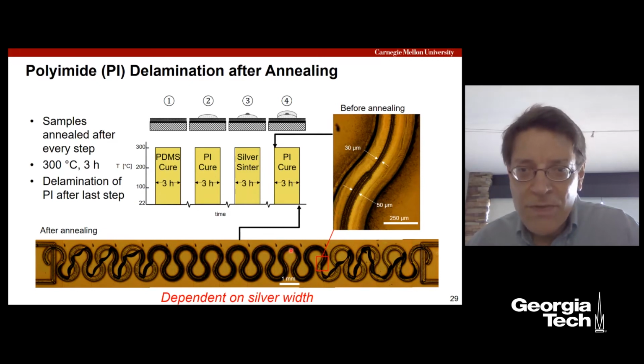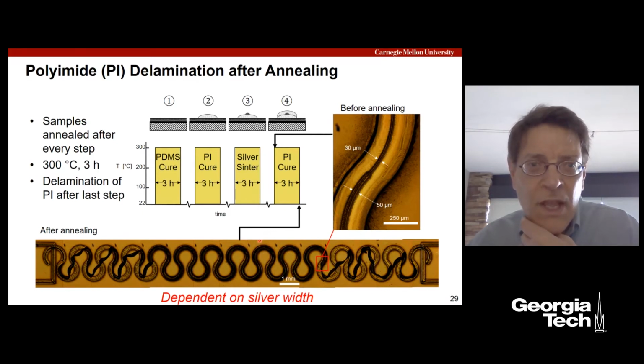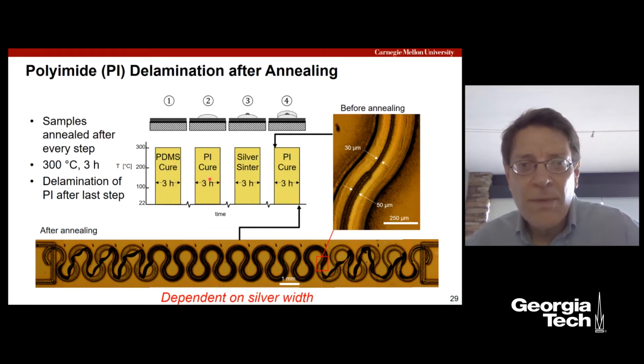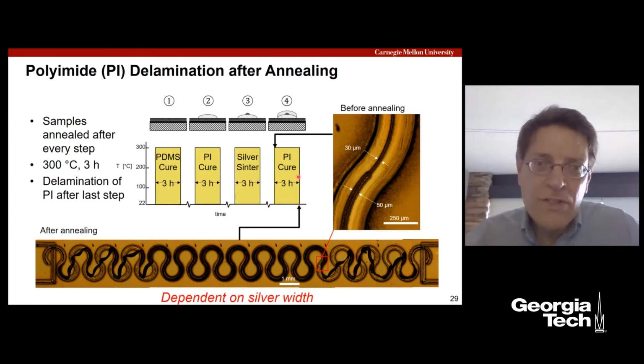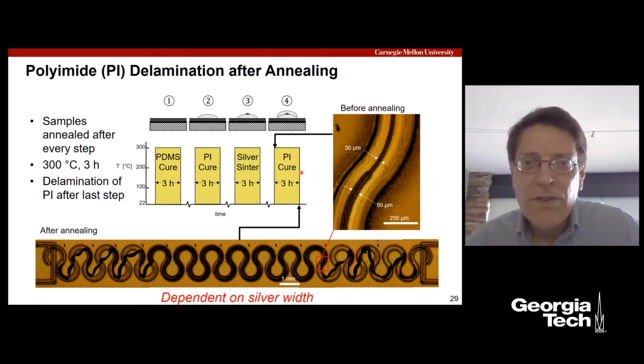What's happening is we're getting delamination in regions where we have 50 micron wide lines at the ends, and where we have the thinner 30 micron wide lines, we don't see the delamination. And this delamination is happening at the very end of our process, where we do the 300C PDMS cure, then the polyimide cure, and then the silver sinter, and then we aerosol-jet the polyimide on the top and do a cure. And it's during that cure that we're seeing this delamination.